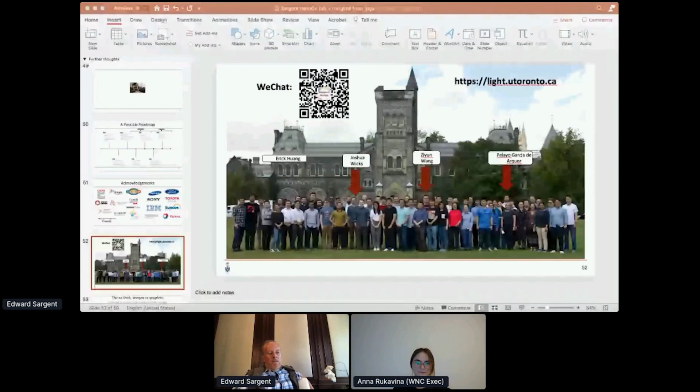And it's in solar electricity that it's shown particularly rapid progress. It's kind of amazing, actually, what the perovskite community has done in terms of getting to solar power conversion efficiencies, but from this liquid-processed, room temperature-made material that's a thin film, half a micron or a micron thick, compared to silicon solar cells that require such high temperatures and that have benefited from decades and decades of gradual performance improvements in manufacturing. So it's amazing how fast the perovskites have moved.